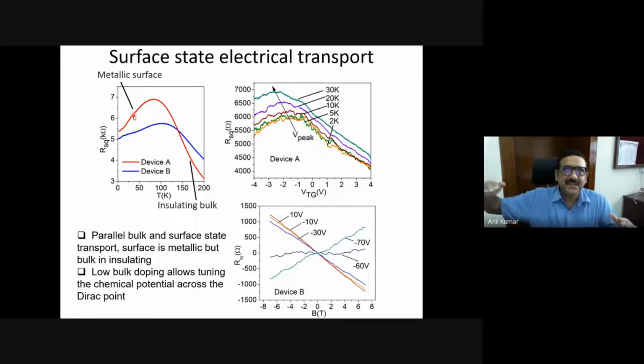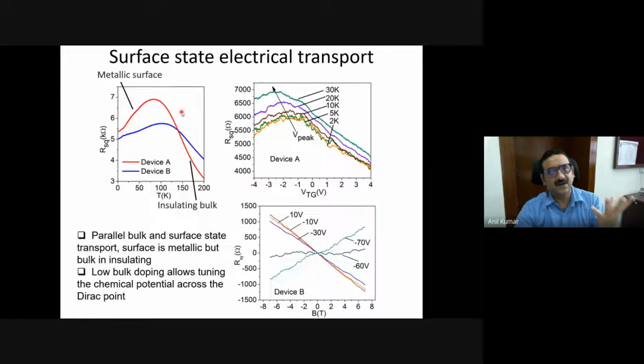But suppose the resistance of this bulk and the resistance of this surface become almost equal, then it reaches a point like this. And then onwards, the conductivity of the bulk takes over and the resistance goes down. So my first proposal is that I have a topological insulator whose surface is conducting and the bulk is insulating. People may argue that this is not the proof, because there are different kinds of material which show a metal insulator transition. So this may not be the only proof.